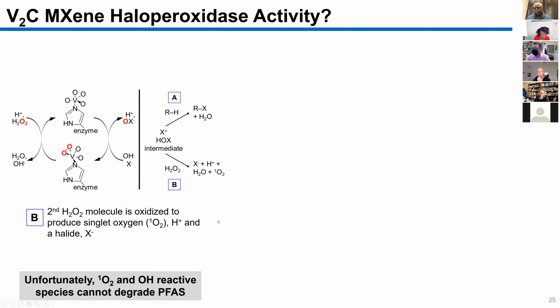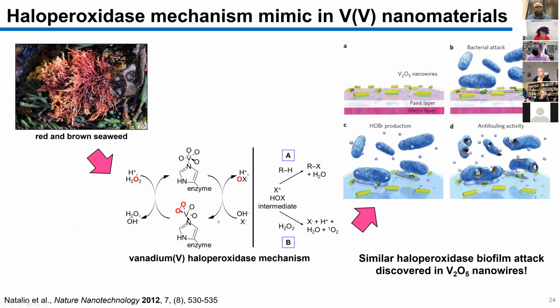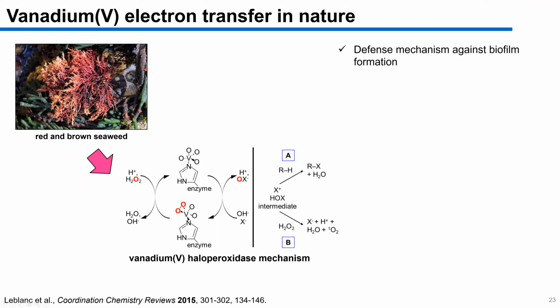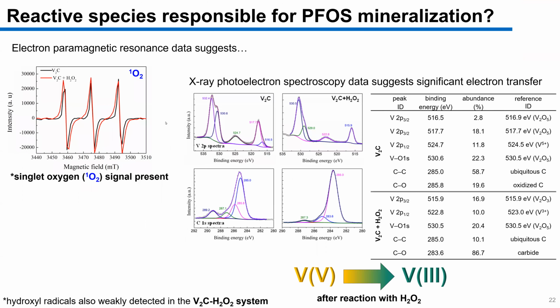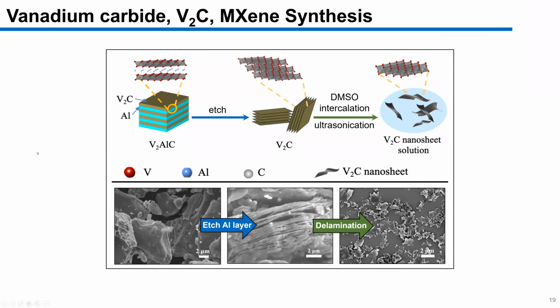Let's see. So the vanadium carbide within the MAX material, you mean? Yeah, the starting material that we use. Right. So when we use the material, we start with the MAX phase, which is synthesized in the lab. The processes by which you generate either vanadium aluminum carbide or titanium aluminum carbide or other MAX phase structures that could then be etched to form MXene structures, that's a complicated setup for us to achieve.